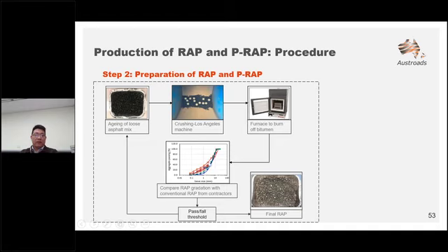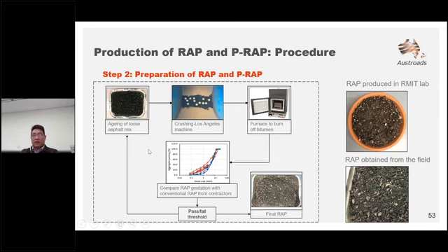But if the RAP gradation failed to meet the threshold, the trial continued by increasing the number of revolutions in the Los Angeles machine, and similar steps apply again until the gradation of the RAP met the threshold. We can see here two pictures. The top one is the RAP produced in the RMIT lab, and the other one is from the field. Visually, they look quite similar.